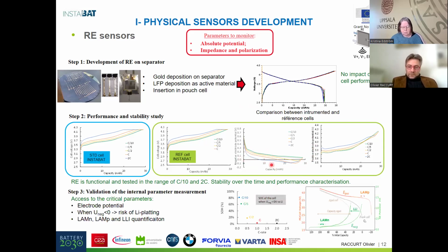With this kind of information, we can manage different information about the aging or the risk of degradation mechanisms in the cell. For example, we can determine the critical C rate for the SOH to limit the risk of lithium plating, and we can also access the potential of each electrode compared to the potential of the cell, and in this way, by monitoring the variation of this potential, we can access the different loads of active material at the positive side, negative side, and the lithium inventory. And we use this kind of sensor during the aging test to monitor all these parameters.